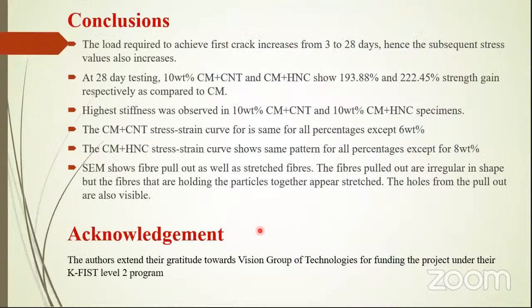So coming to the conclusions, what we have seen is that the load or the stress required to achieve the first crack increases from 3 to 28 days, and hence the stress also increases. What we found is at the 28-day testing, 10% weight of CM and CNT samples and CM and HNC samples showed nearly 193% increase in strength in CM CNT samples, and 222.45% strength gain in HNC samples as compared to normal cement samples.